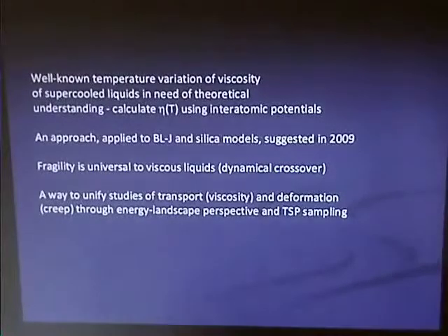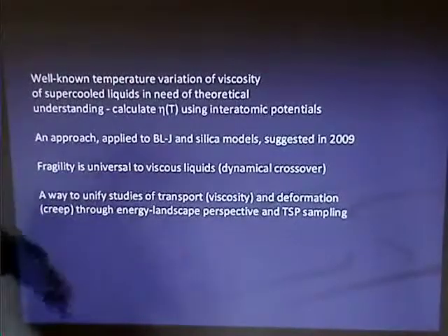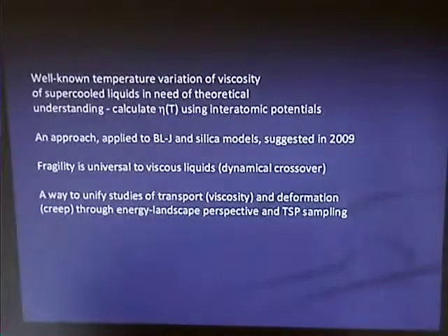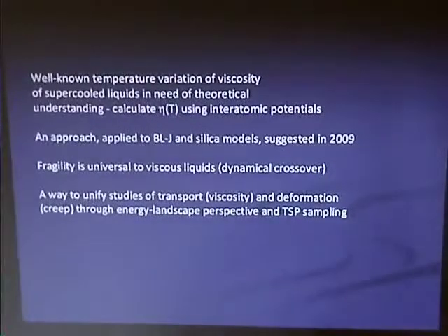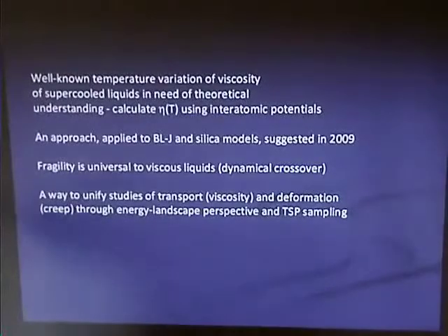Our claim, based on some things I'll put in front of you, is that actually fragile behavior is universal to all viscous liquids. Namely, if you have a liquid that you call strong or fragile, you would have something else that's the other part. So a strong liquid is silica. We claim silica actually shows fragile behavior at high enough temperature. Experiments don't show that because experiments don't go up to high enough temperature. But if you have a method to calculate this, you can predict that.